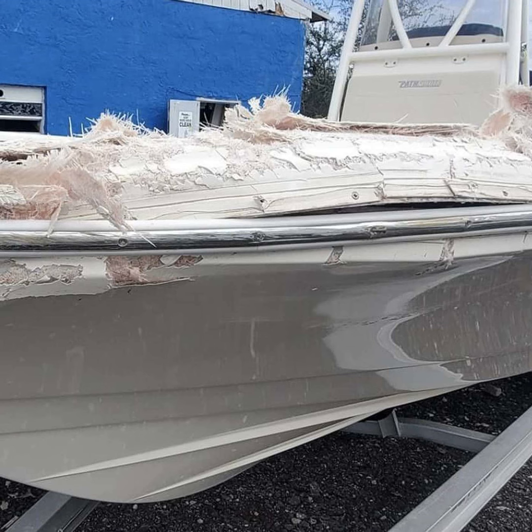And once you have that in there, if you got a decent job with the hot glue, you can cut that string. Sometimes you can't get it to hold, and you actually have to hold some tension on that string the whole time and just glass one layer over that of 1.5 ounce or 3/4 chop strand mat or something that's going to have just enough strength to it that you can now run your bubble buster and your roller against it once it kicks. So once that cures, cut your string, scuff it all over, and now what you have is the entire bevel thickness ready for you to apply glass to it, but you've got a solid area to build glass over. That makes sense the way I described that?